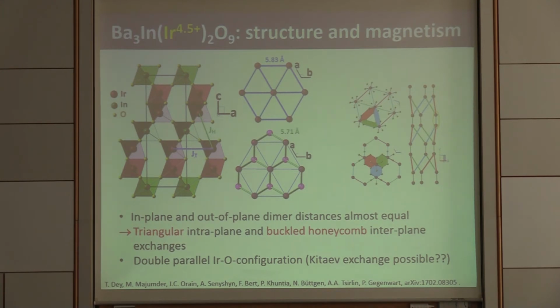So now of course we need single crystals to really determine the anisotropy and to get information on whether this buckled honeycomb interaction is more important or the in-plane triangular exchange. But what we could say from the structure is that in any case, for both, we always have a double parallel iridium-oxygen configuration, and perhaps that would also allow Kitaev-type exchange in that material.